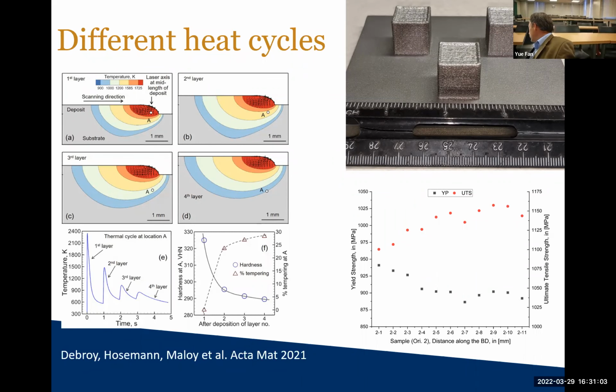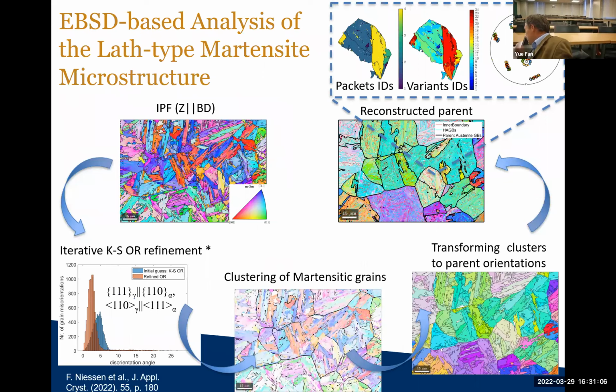So the question then is, okay, what does the microstructure look like? And Shmuel, a postdoc working with us, is really good in EBSD. So he records all these different layers, the EBSD microstructures, and uses them to calculate packet sizes, grain sizes, and microstructural features from the EBSD. He calculates the cluster densities, the lath dimensions, all these things, and can reconstruct what this microstructure looks like when you deconstruct it into grain sizes.